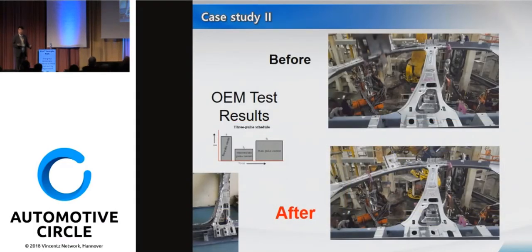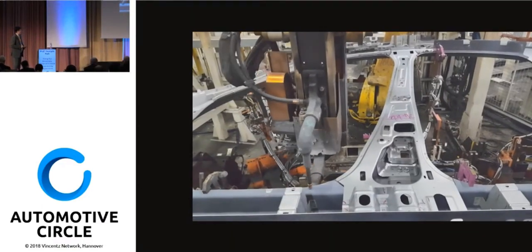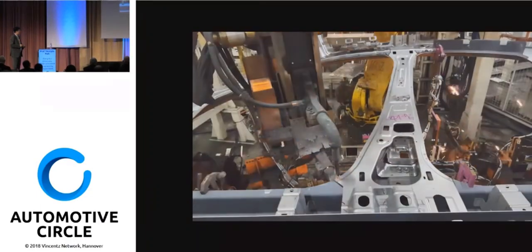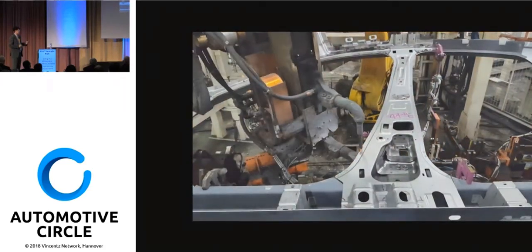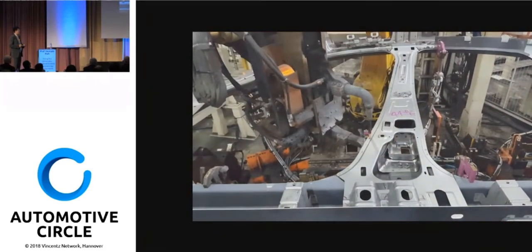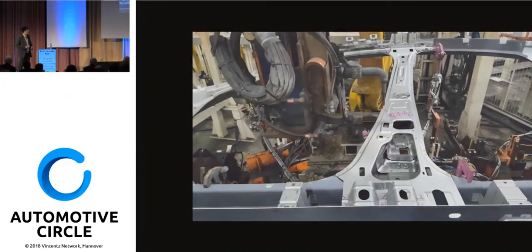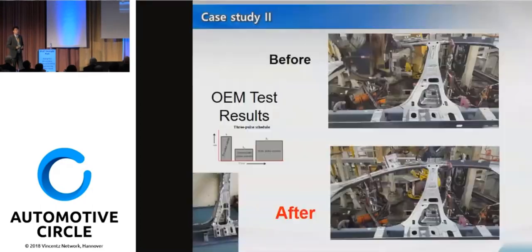With all of these pre-pulse and multi-pulse schedules, there was one OEM that wanted to test this result. And this is their production line condition before. And this is what we provided them: the optimal welding pulse current profile with 3-pulse, 2-pulse, based on our given material gauge and grade. So this is how they were doing the welding. You can see very large spatter happening here. Another large spatter, and then another large spatter, with a very weird sound, but they are suffering from the large spatter with this production condition.